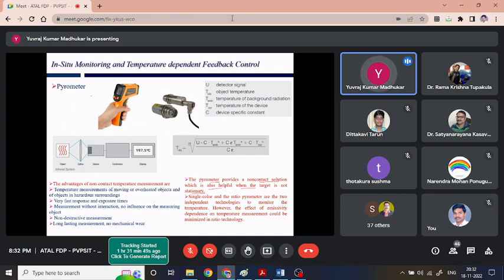Now, these are possibly the images of the pyrometer we might have been seeing. In the field of pyrometers, a recently developed new technology has come into the picture, called the ratio pyrometer. There are two independent technologies, a single color and the ratio pyrometer. In case of a single color, it takes the spectrum only from one zone, and in a ratio pyrometer, it takes the spectrum of a defined zone, with two independent monitors and independent temperatures. So we are getting the object temperature T1 and the temperature T2 of the same object, and we are dividing T1 by T2. Since the emissivity over this small spectral distance is supposed to be almost constant, the emissivity term is going to get cancelled, and we are going to get the almost absolute temperature.